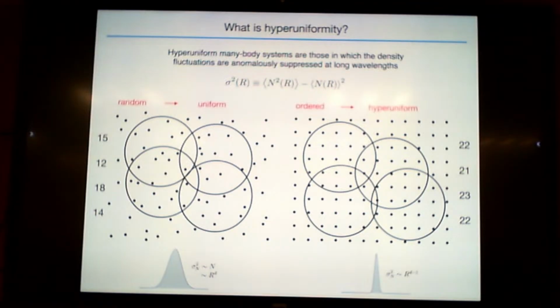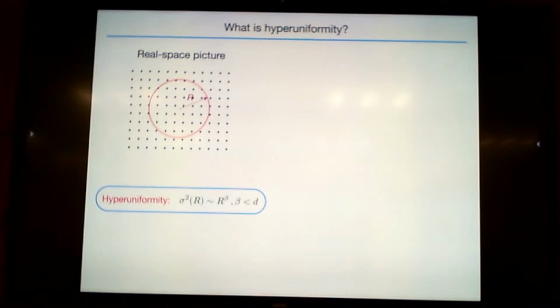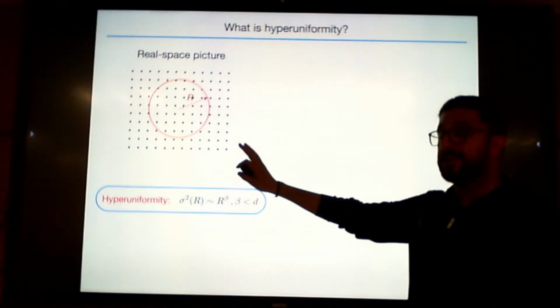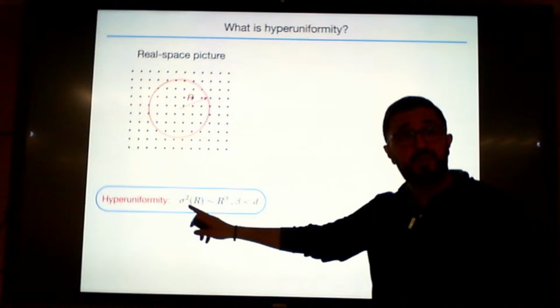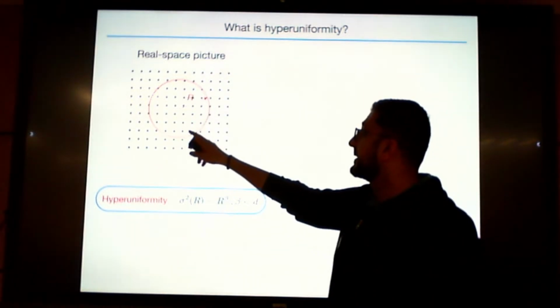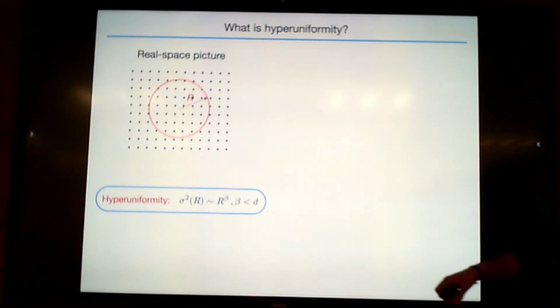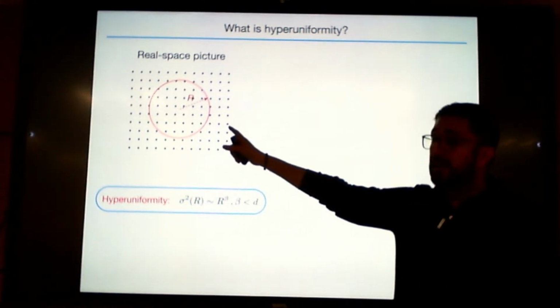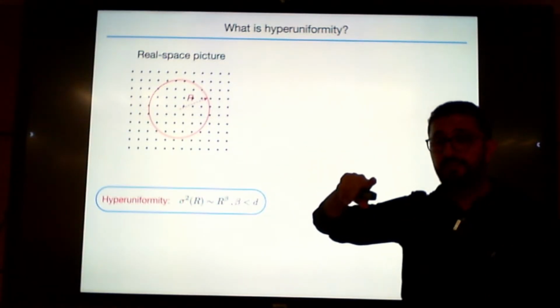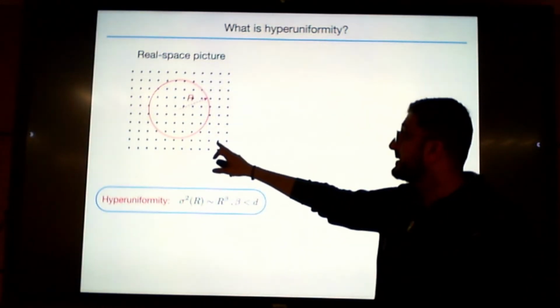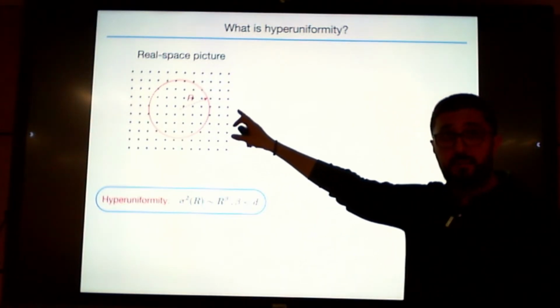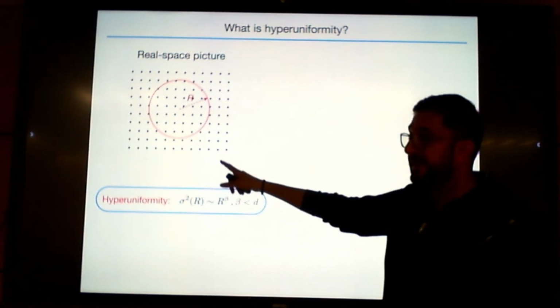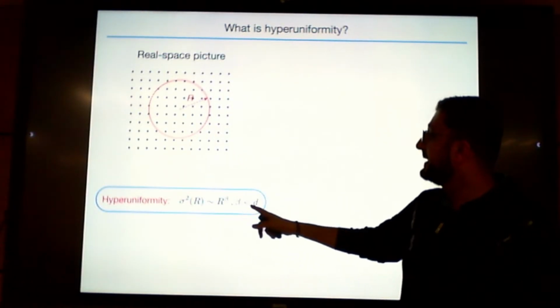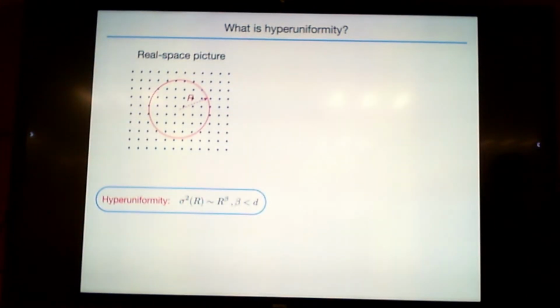So to quantify this further, this is the real space picture I was just mentioning. Whenever the number variance associated with the number of particles inside an observation window of dimension r grows slower than the area, in this case it grows as r to the power 1, but in principle it can take any exponent beta. Whenever this beta is smaller than the dimension of the system, we say the system is hyperuniform.